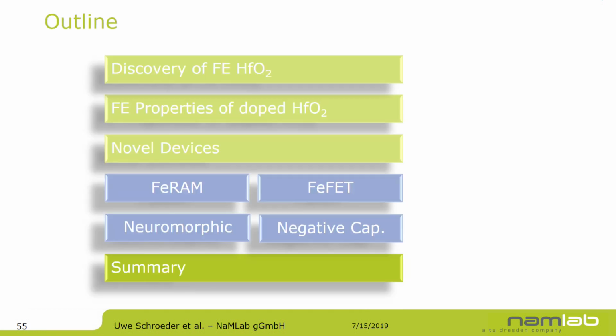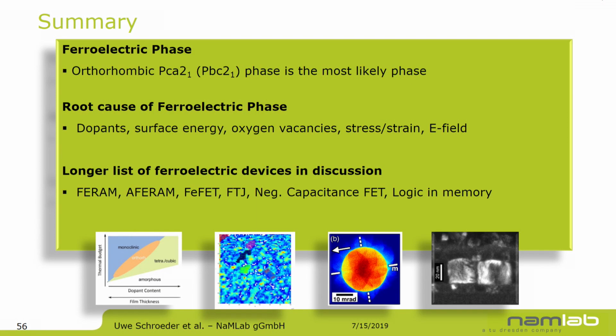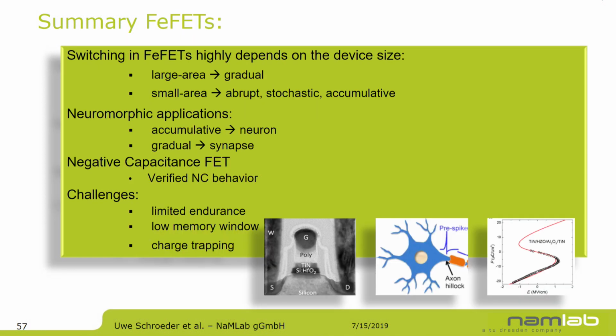So with this, the end of my talk, I'd like to quickly summarize. I hope I could show you the ferroelectric properties in hafnium oxide, and I showed you only one part of the root causes. There are more than just the dopants to form the ferroelectric properties. There's a longer list of different devices you can build with hafnium oxide. And looking into the FeFETs, I hope I could show you that the large FeFETs have a gradual switching, which is nicely usable for the synapse case, whereas the small devices have abrupt switching, and for this we can use them for the neurons.